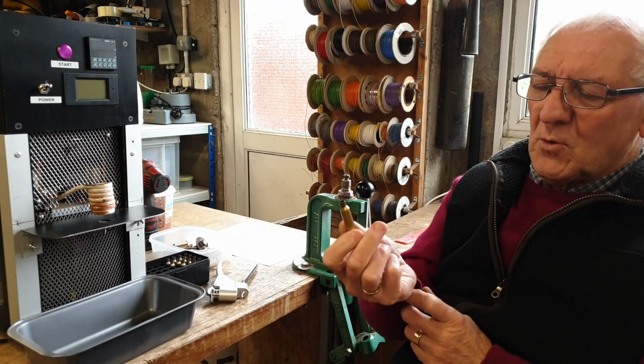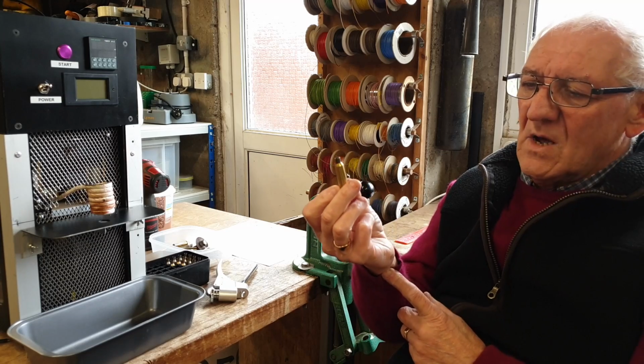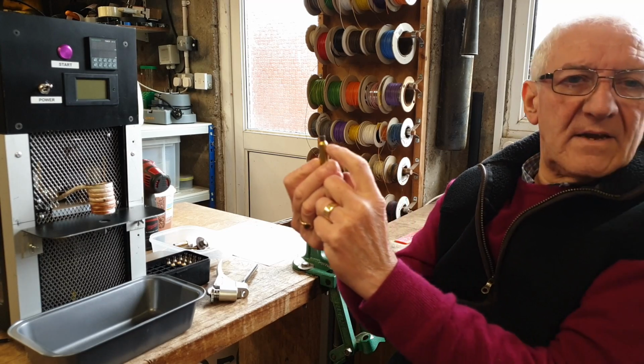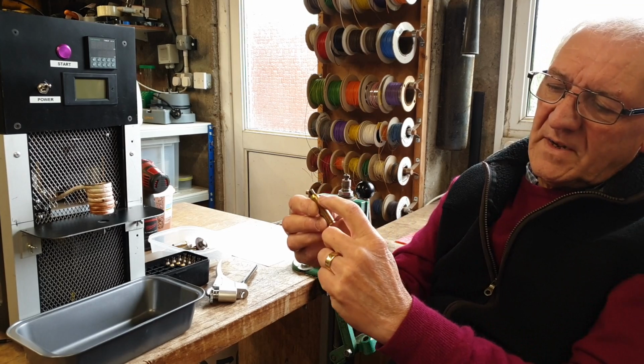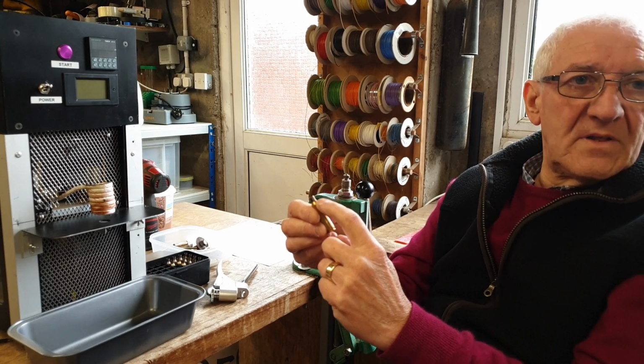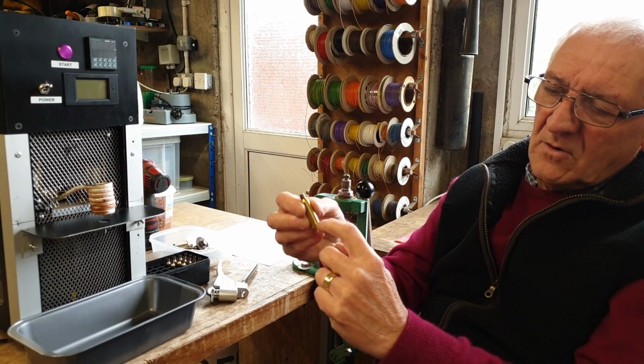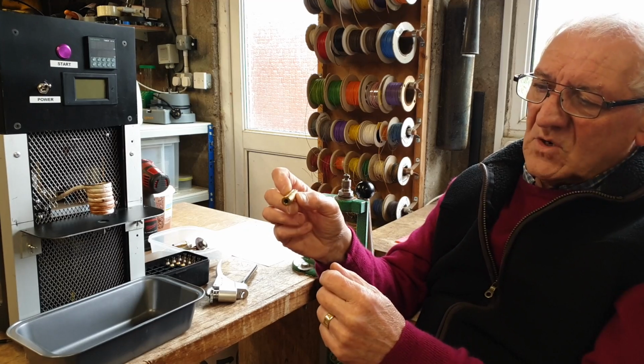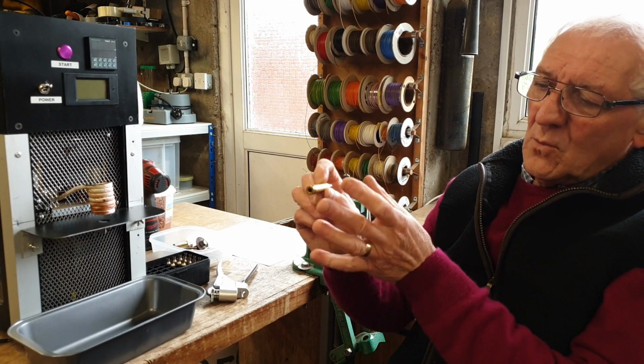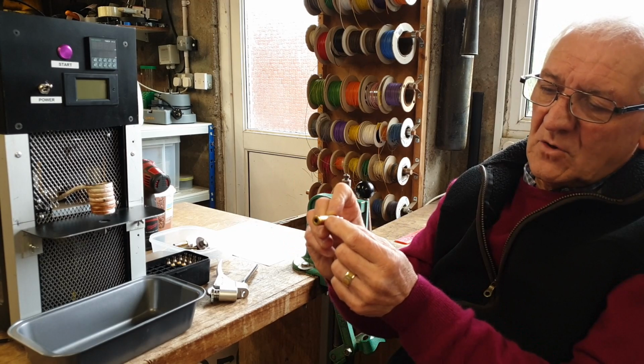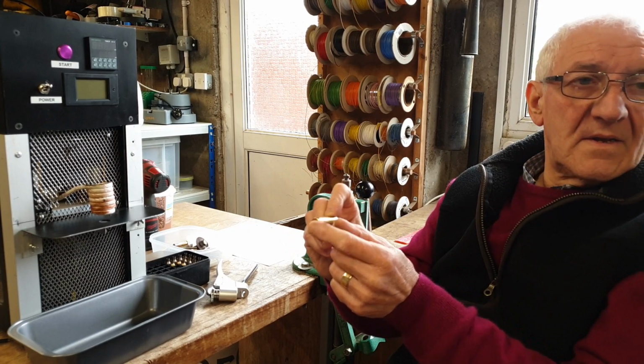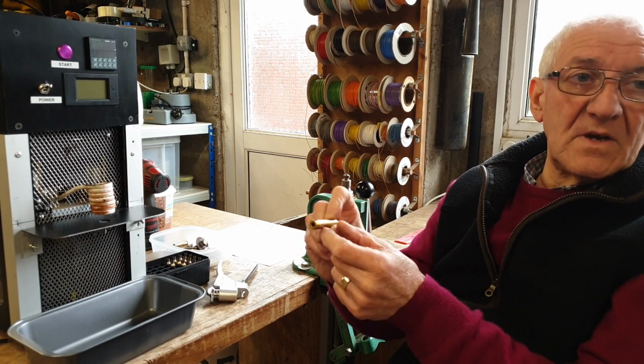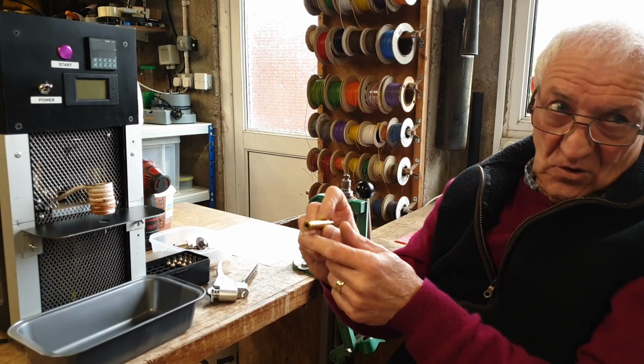The other thing that's important to note is that when we anneal the brass, we only want to anneal the neck and the shoulder. We don't want to anneal all the way down the body of the brass. We don't want this area down the body to become soft, because what can happen then is that when the cartridge is fired, you can eventually cause the cartridge to part down here. And a body failure when you fire a cartridge is not good news.